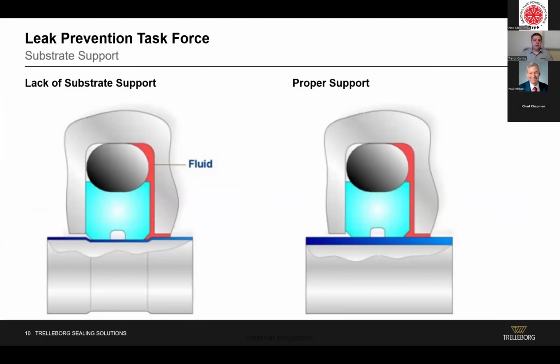But when you look at the substrate and the coating, it's a combination of how they go together. If the coating is supported by too soft of a substrate, then it can crack, it can get deformed, or it can even be carved into. The coating can get carved out under high pressure load. And so what we want to do is have a substrate that's hard enough that it can support that coating, and then a coating that's thick enough that it can support the seal. It's a combination of those two working together.